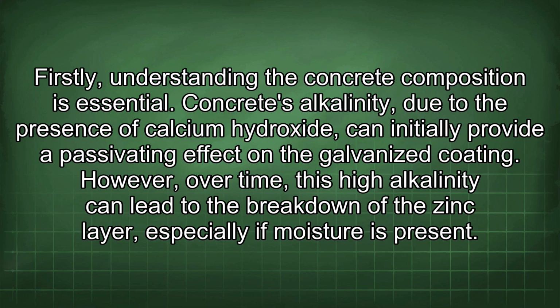Firstly, understanding the concrete composition is essential. Concrete's alkalinity, due to the presence of calcium hydroxide, can initially provide a passivating effect on the galvanized coating. However, over time, this high alkalinity can lead to the breakdown of the zinc layer, especially if moisture is present.